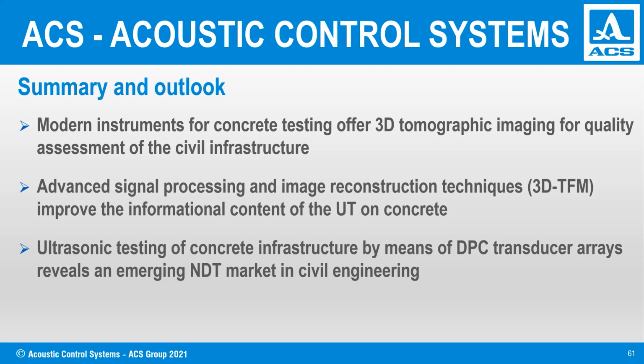That means you would have to have different concrete blocks, I mean different concrete types, with different sizes of rebars and different depths. And then, after having these calibration blocks, you could really measure the rebar diameter by just estimating the amplitude of the indication. But unfortunately, this is a very expensive way.